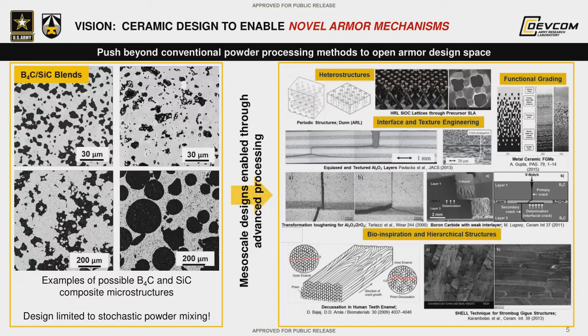That way we can do advanced things like create interface or texture engineering to control the failure propagation and the crack modes, do things like functional gradients, build in residual stresses into our microstructures, or create these sorts of laminated hierarchical microstructures, things like brick and mortar microstructures or nacre-like structures, which can advance the mechanical properties above what you can get just by stochastic mixing of one or two materials.